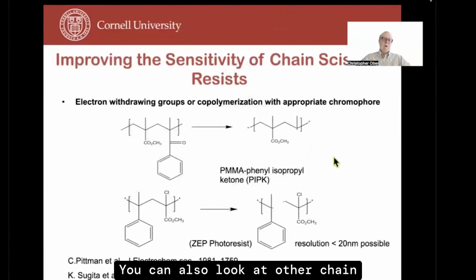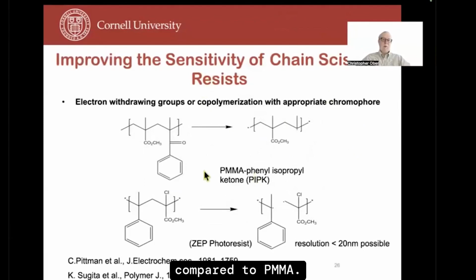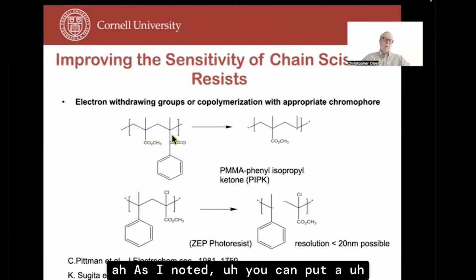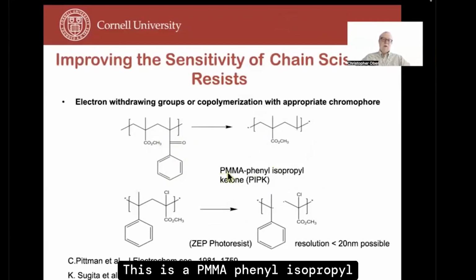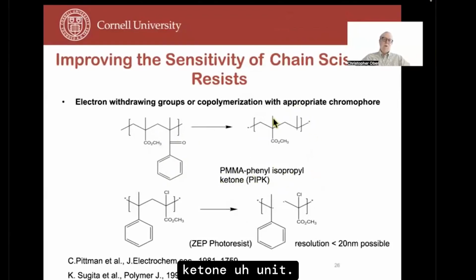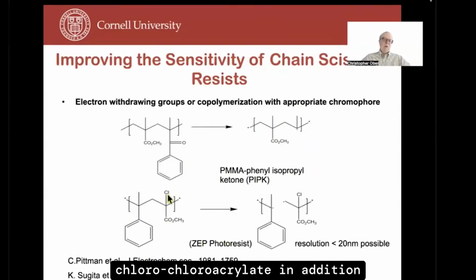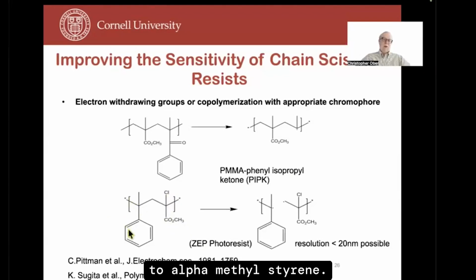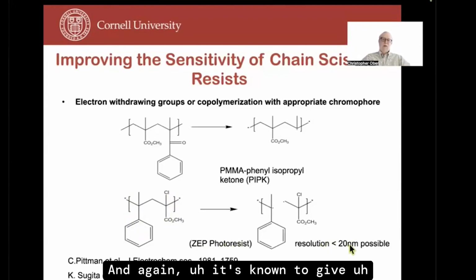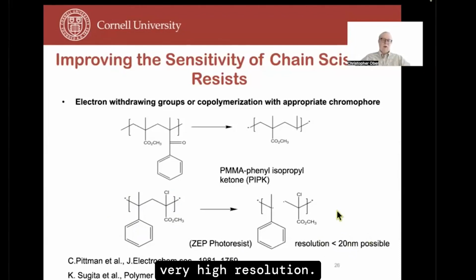You can also look at other chain scission systems and improve the sensitivity compared to PMMA. As I noted, you can put a phenone type of group onto that. It's more easy to cleave. This is PMMA, phenyl isopropyl ketone unit, and so that is sensitive to radiation. And you can also use a chloroacrylate in addition to alpha methylstyrene. This is the so-called ZEP composition. It's much faster, and again, it's known to give very high resolution. So higher sensitivity, higher resolution. What's not to like?